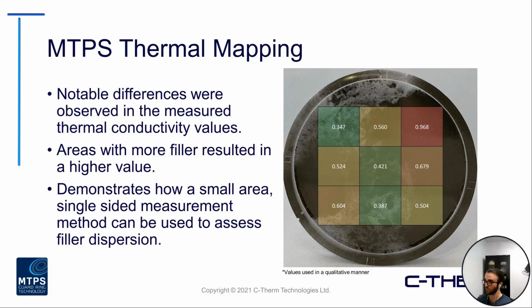In the upper left corner, indicative of spot number 2 there, you have a very low effective conductivity measurement coming in at about 0.347. Whereas to the right of the image there, where you get more of that concentrated buildup of the filler on the backside, it's coming in at an effective conductivity value almost 3 times larger. So in this example, it's very clear to see that the dispersion is not uniform.